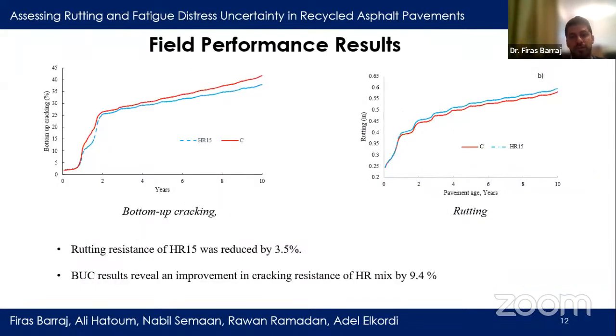The results of the permanent deformation or rutting predictions after 10 years indicate that the rutting resistance of RAP mixes was reduced by 3.5%. These results come in agreement with the findings of E-star testing that revealed softer modulus at higher temperature for the mixes incorporating RAP. On the other hand, bottom-up cracking results revealed an improvement in cracking performance of RAP mixes by 9.4% compared to the standard HMA. This also aligned with the findings of E-star testing showing stiffer modulus, which is more brittle, for the standard HMA.